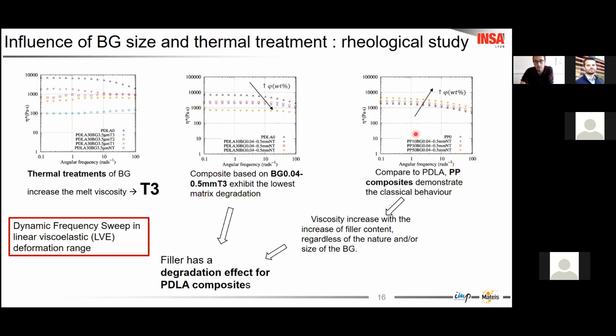When the filling ratio increases, like in polypropylene, normally the viscosity has to increase. But in fact, when the ratio increases, the viscosity decreases, showing that the degradation effect is more important than the reinforcement effect with PLA and bioglass.